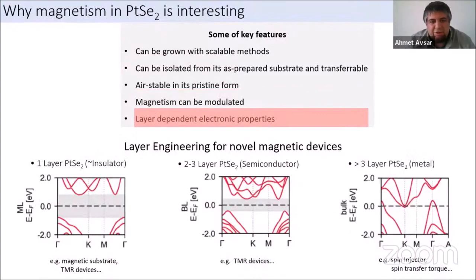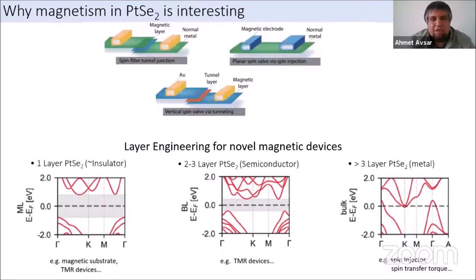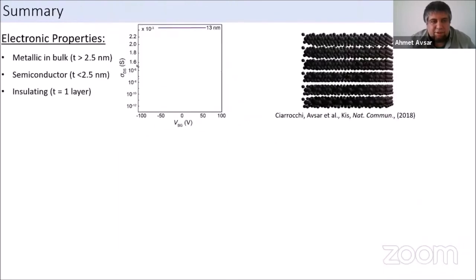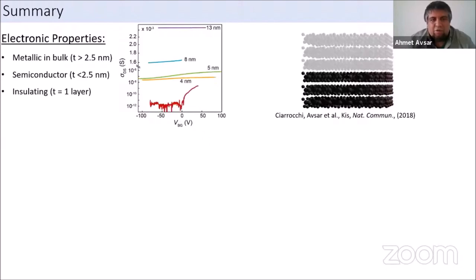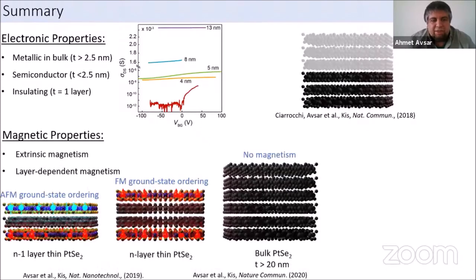And the material also has a layer-dependent electronic structure, so it can be used as a magnetic insulator or a conducting magnet in several applications. In summary, the material is showing thickness-dependent properties. It's a metal in bulk, a semiconductor below 2.5 nanometers, and an insulator as a monolayer. The material also shows a magnetic response below 20 nanometers, and it looks like it has a thickness-dependent magnetic ordering.